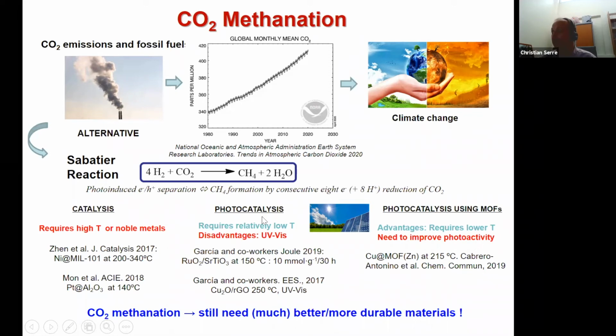You can use photocatalysis with oxide or graphene oxide or MOF. There are some good performances with, for instance, perovskite or copper cluster on RGO, but they work only in the UV-visible range. In the field of MOF, there were some reports using some copper and zinc MOF at 215, but the yield was relatively low. It worked under visible range, low temperature, but with a low yield. So there's still a need to have material that works well under visible light, lower temperature, with a good yield.